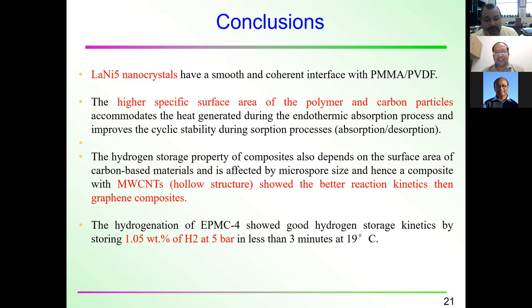And I used two different materials, multi-wall carbon nanotube and graphene sheet. Multi-wall carbon nanotube has a hollow structure and gives better reaction kinetics than graphene. And this is one example of the hydrogenation process. At 19 degrees Celsius, room temperature, the hydrogen storage capacity for one of my samples, EPMC4, is 1.05%. That means if you have 1 kg of this material system, you can store 1.05% of hydrogen by weight at 19 degrees, that is room temperature. The pressure is a little bit higher, but I need to work in this area to make it just 1 bar atmospheric pressure. Then only can I claim that this material can be used for onboard application.